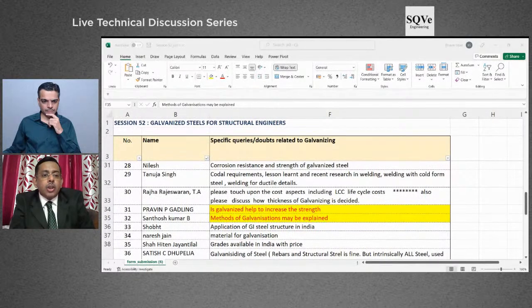So the basic difference is, in the continuous galvanizing process, you have an annealing, and in the cold rolled sheet, it's a faster process, but the coating thickness is low. But in the case of batch galvanizing, you have thicker components where you put flux. Flux acts as an agent between the galvanizing and the steel surface. After that, you do the galvanizing. The process is slower, the time is higher, and you get a higher coating thickness. This is batch galvanizing, and most of the structural engineers are interested in batch galvanizing.